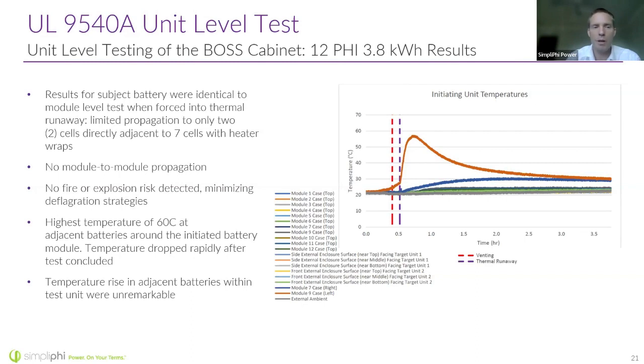As this test was being run, there was no fire or explosion detected outside of the batteries, right? So there was no big fire, even though we're trying to force a fire to happen. There was no module to module propagation. That means that even though battery 8, we forced it to off gas, we forced it to go through a thermal runaway by actually placing heaters inside it, batteries number 9 and number 7 right next to it did not go into thermal runaway themselves, right?